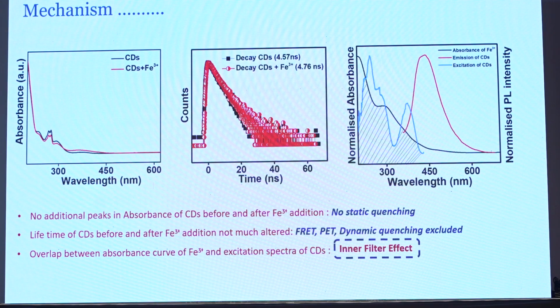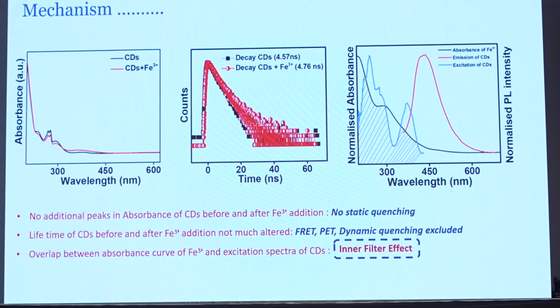We have used absorbance spectroscopy, PL spectroscopy, and luminescence decay study for identifying the mechanism. Absorbance spectra shows that even after the addition of ferric ion, no additional peak is observed. So, the possibility of static quenching can be excluded. Now, we have checked the decay studies, which show that the decay lifetime is not much altered even after the addition of ferric ion. The possibility of FRET, PET, and dynamic quenching can be excluded.